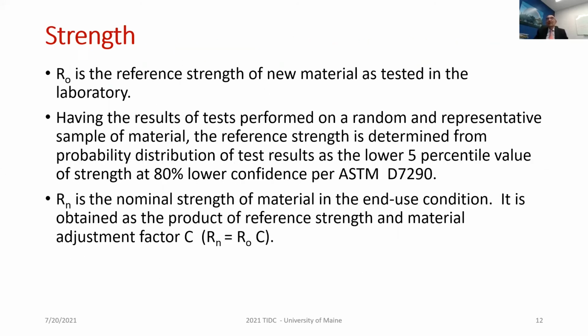Strength. Strength is defined with reference strength, which is new material as tested in the laboratory following ASTM standards. However, what do we do with the test results once we obtain them? Here is what we rely on, an ASTM standard that has been published, where we look at the reference strength as the 5th percentile value of the test results with 80% confidence. Now, confidence has to do with the size of the sample that you are testing. And once you have the reference strength, the nominal strength is the strength in the end-use condition.